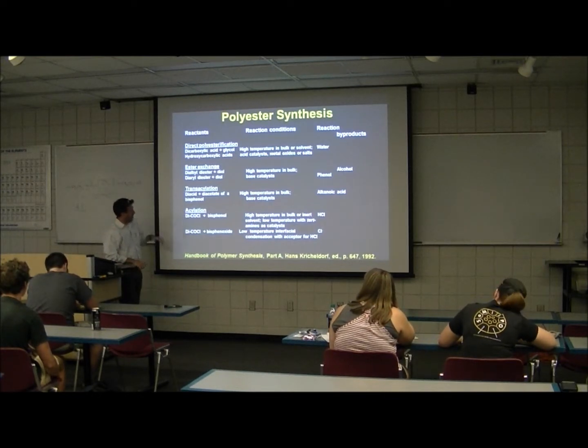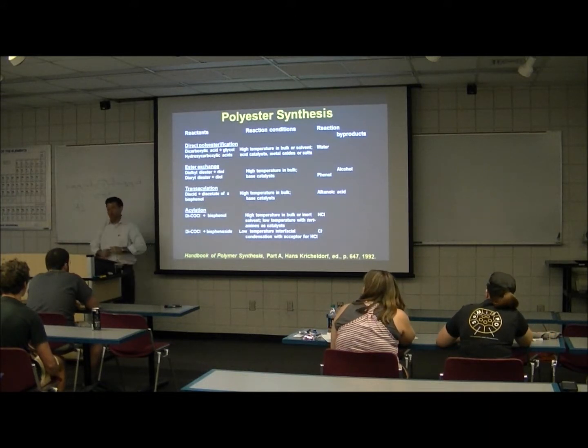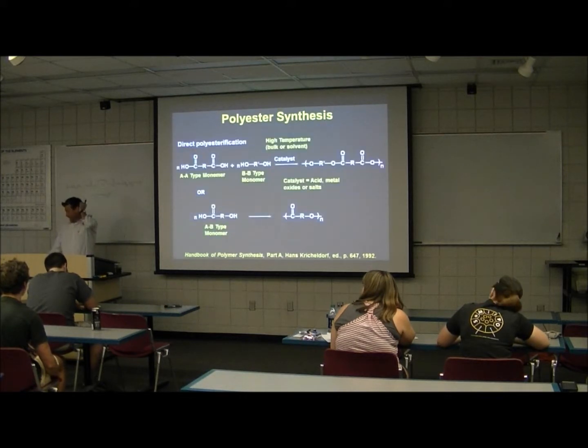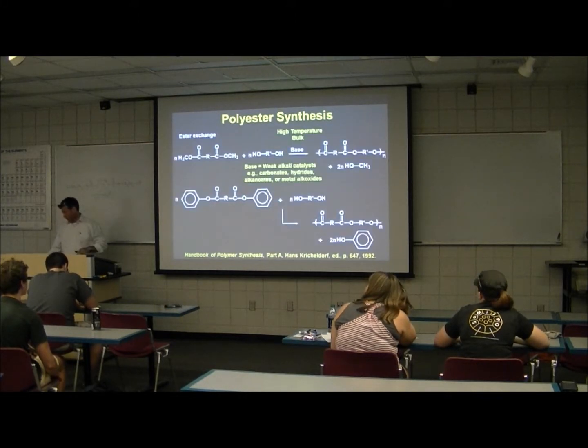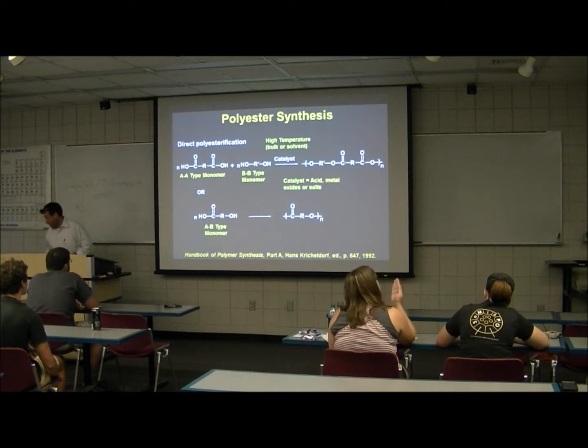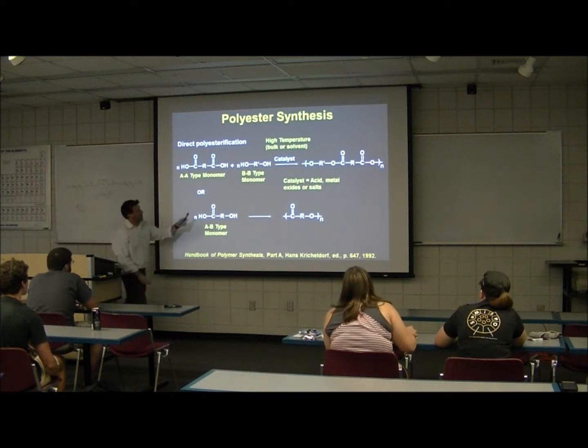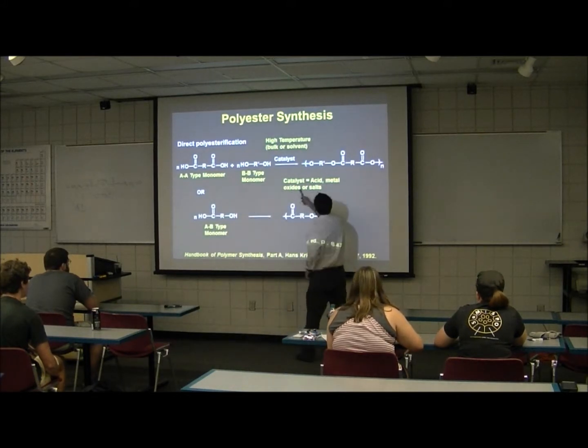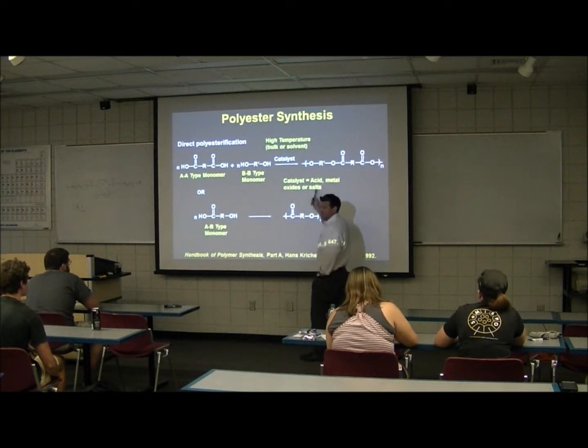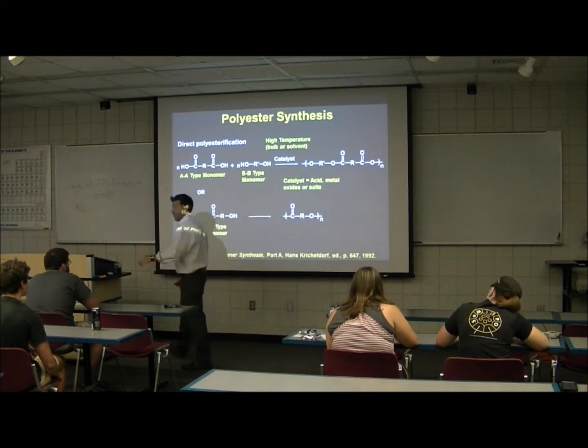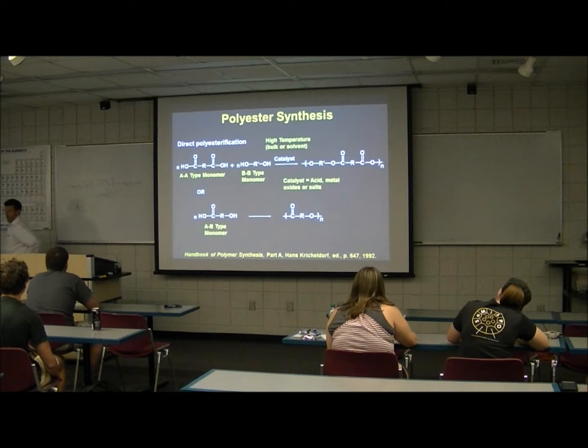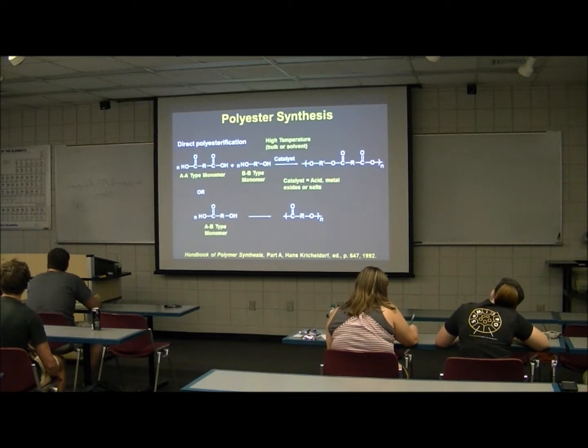And then acylation, which is the thionyl chloride or phosgene route to getting acid chloride. So mechanistically, what's important as I go through these next 4 slides real quick, direct polyesterification typically uses acid, metal, or metal oxides or salts. And the one that's most common for high temperature synthesis is tin oxide. Now there's lots of other tins that are used, but when you do very high temperature reactions, you use tin oxide. And that tin oxide actually rearranges to become like the salt, not the salt, but the adduct of,